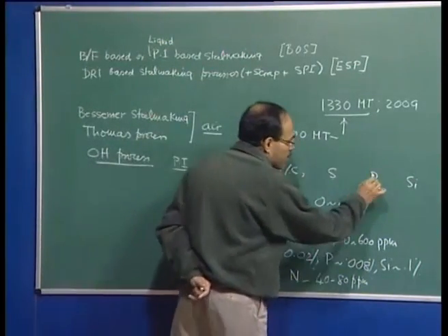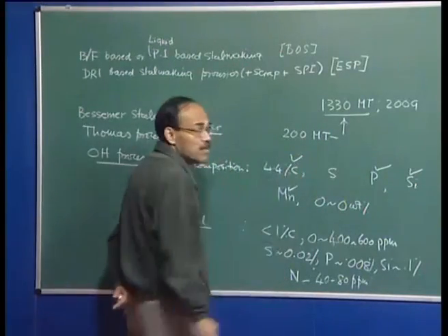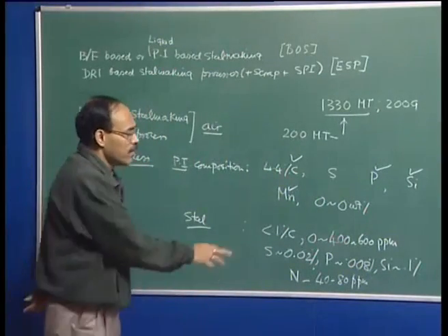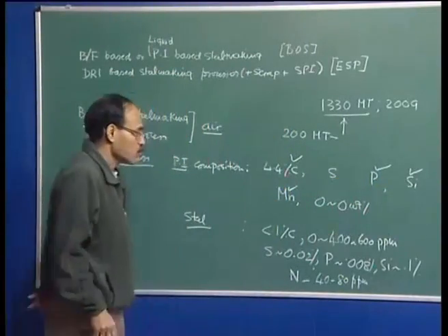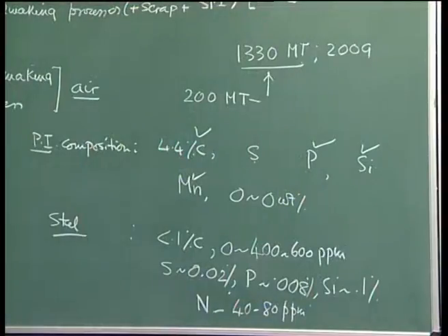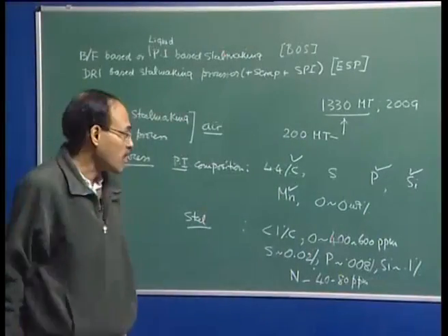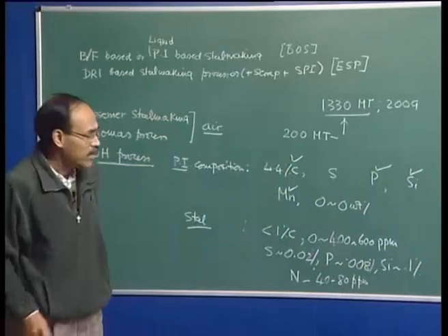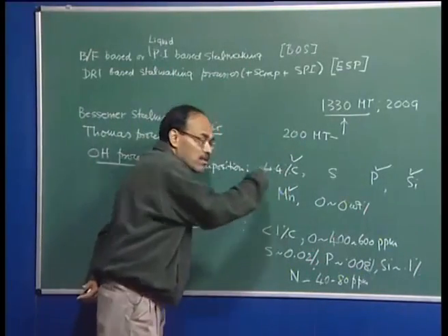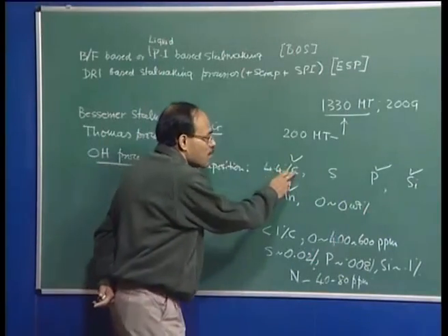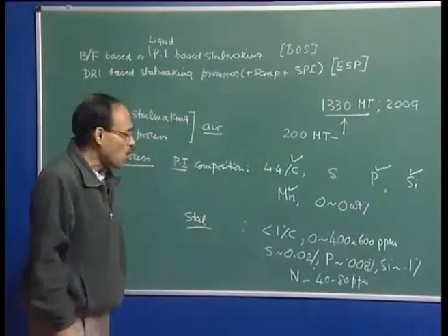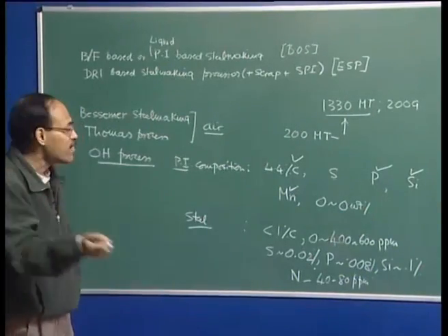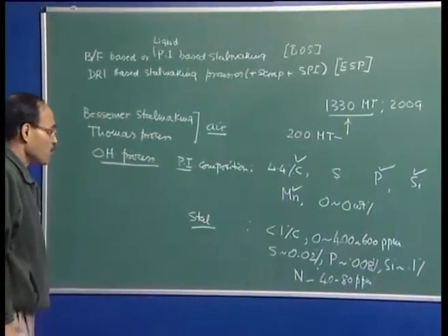To remove phosphorus, silicon, manganese, carbon, you will study this in detail in the principles of steel making. They have higher affinity towards oxygen. In the Ellingham diagram that I will discuss when I talk about the science base of steel making under the section of thermodynamics, we will see that carbon, phosphorus, silicon, manganese have great affinity for oxygen. And that is why when you pump oxygen through molten pig iron, these elements react with oxygen and get oxidized. So, steel making basically is an oxidizing refining process. You introduce oxygen and thereby you refine the impurities which are present in the pig iron itself.